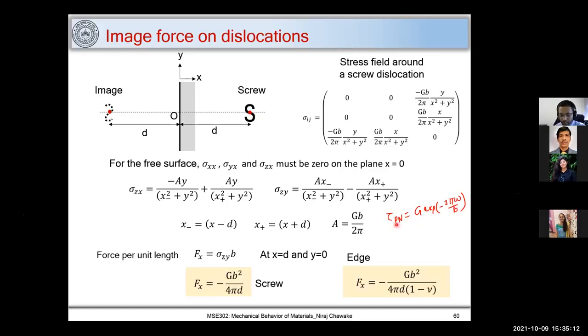If this tau PN, let me write it down also, is greater than Fx, then you don't have to worry about image force. But if this tau PN is less than Fx, that means this force is more than the Peierls-Nabarro stress, and your dislocation can vanish, or it can come to the surface. So whatever you may be seeing in your sample may not be the dislocations which you are interested in.